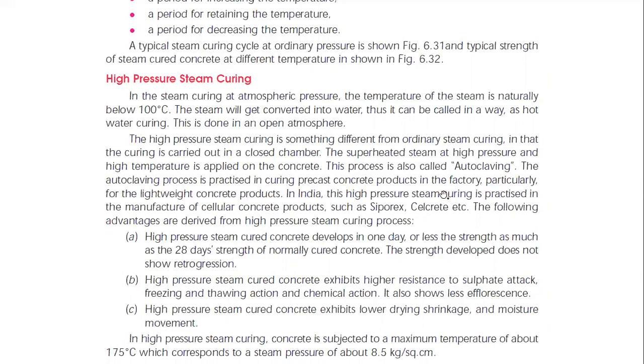So basically the following advantages are derived from high pressure steam curing. High pressure steam cured concrete develops in 1 day or less the strength as much as the 28 days strength of normally cured concrete. The strength developed doesn't show retrogression. High pressure steam cured concrete exhibits higher resistance to sulfate attack, freezing and thawing action, and chemical action. It exhibits lower drying shrinkage and moisture movement.